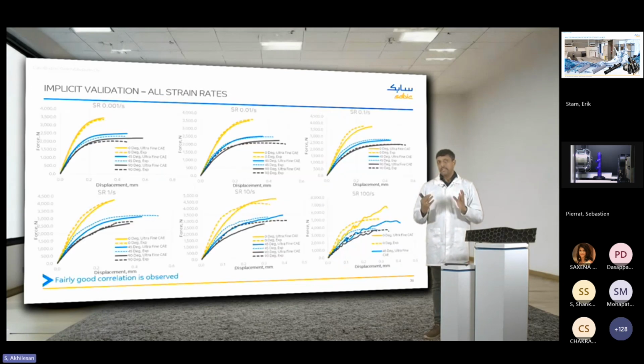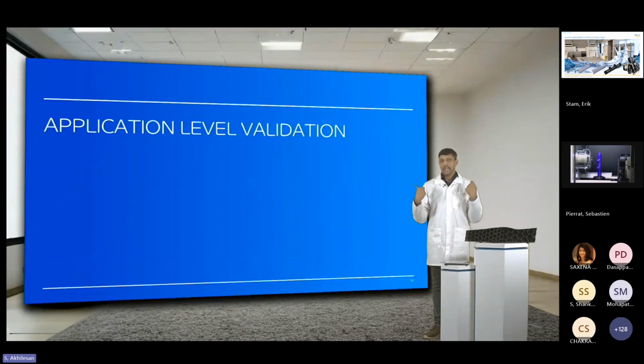And we do this not just at one condition, but at all the conditions at which we create these Digimat models. And in the case you see here, this is the implicit validation done in Abaqus implicit solver for 6 different strain rates. And we see that all of these models accurately predict, or fairly accurately predict, what we observed experimentally, with a little bit higher variation at higher strain rates, which is expected. Now that we gained confidence that at a coupon level or a specimen level, we are establishing good correlation of the models and the experiments, we will move on to what we do at the next level.